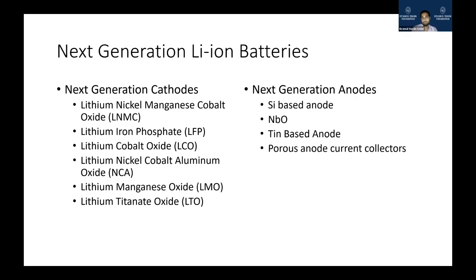So the porous anode current collector is also something people are looking for, and I am also working on it. For example, if you have more surface area, that means you can accommodate more space for the lithium. So people are working on making the current collector porous, so that you can have more surface area. And when you have more surface area, that means you have more space for putting your lithium inside.